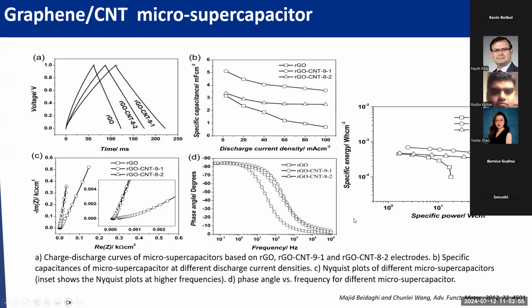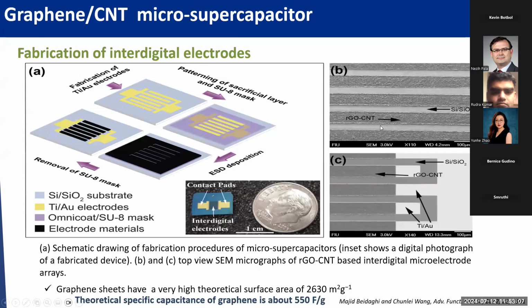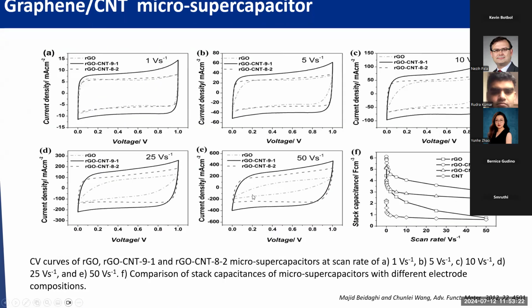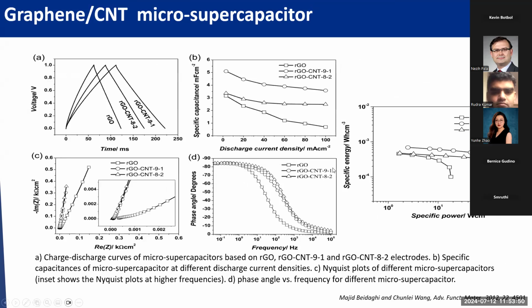So compared to typical thin film capacitors, we have much better performance. The reason is, first of all, we are making the micro electrode, so the distance between the electrodes is very short, and the diffusion path is short. So that's the first reason. The second reason is this RGO CNT has really good performance, not only in terms of energy density, but also a very fast response. And even from the first cycle, we don't have degradation for the RGO CNT composite materials. But for the pure RGO materials, usually in the first 50 to even 100 cycles, you typically see an activation process because the electrolyte ions have to squeeze into those RGO materials.